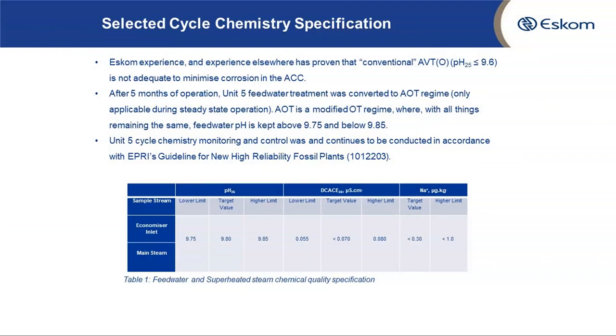Again, if you look at what is AVT, what is OT in terms of IAPWS, you will see that the ranges that we're operating at are well within the IAPWS ranges for oxygenated treatment. But we term this as alkaline oxygenated treatment to differentiate the supercritical units from other Eskom units, since these two stations or power plants are operating at elevated pH when compared to other Eskom power plants. Hence, we adopted the term alkaline oxygenated treatment. But you can still see this as the normal oxygenated treatment according to IAPWS.